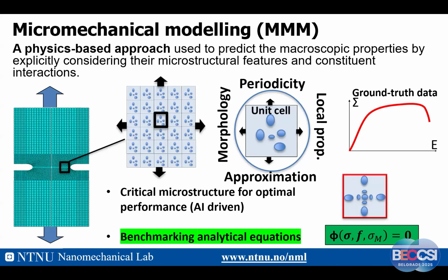Okay? Then what is micromechanical modeling? Micromechanical modeling is a kind of physics-based approach used to predict the macroscopic properties based on local properties and microstructural features. If you look at the specimen on the left, we could easily identify a kind of unit cell model. Here I have a unit cell model in the center, and I have four keywords. First, there should be a periodicity. That means we can repeat this unit cell model. And at the bottom, there is an approximation. It's always an approximation of the microstructure. Microstructure is always more complicated than the model itself.